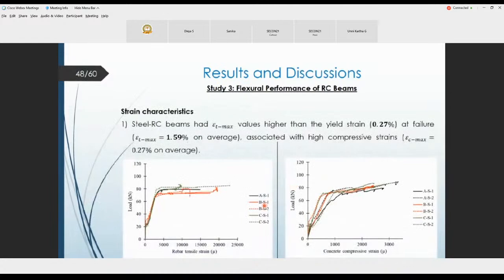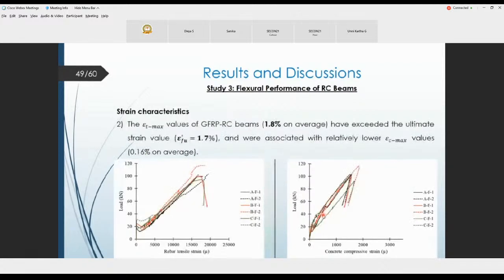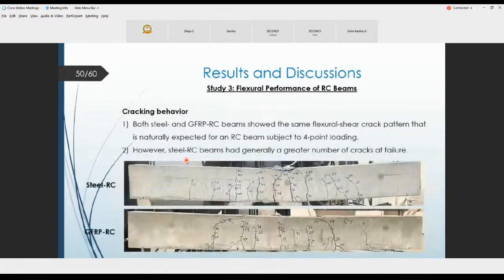In terms of strain characteristics, the steel reinforced concrete beams had maximum tensile strain values higher than the yield strain of 0.27%, at about 1.59% on average at failure, associated with high compressive concrete strain of 0.27% on average. For GFRP, these values were 1.8% on average, exceeding the ultimate strain value of 1.7%, and were associated with relatively lower concrete strain values of 0.16% on average.